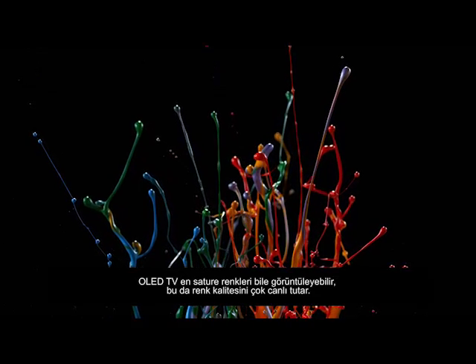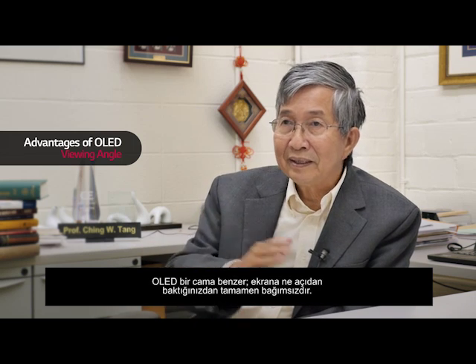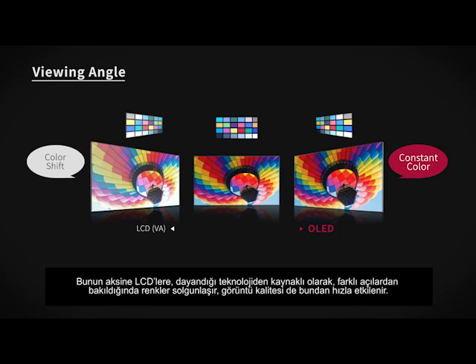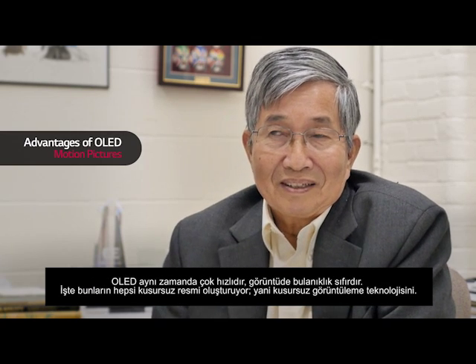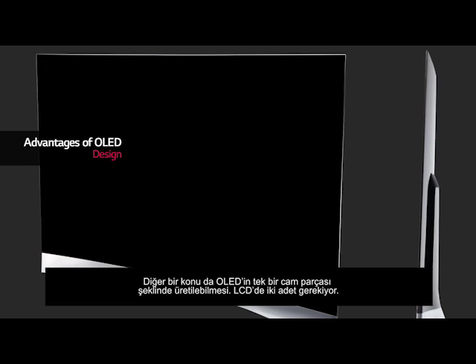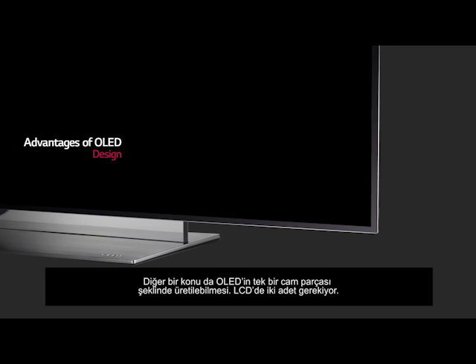OLED can also display the most saturated colors, making the color quality very vivid. OLED is based on a thin film emitter, so it's independent of the angle from which you look at the display. In contrast, LCD — because it's shutter technology — can attenuate light and shift color at different angles. OLED is also very fast, so it has no motion blur, producing perfect pictures. Additionally, OLED can fundamentally be made on one piece of glass, making it thinner and more flexible than LCD, which requires two pieces of glass.